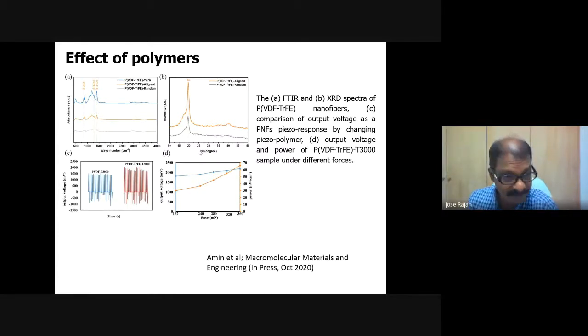But what is disappointing is when you look at the right-hand axis, where the power is noted, even with a potential on the volt scale, the power we are getting is nanowatts. It means that the current through this material is pretty poor because of the inferior current conduction mechanism in polymers. So how do we develop piezoelectric polymers with better conducting properties? What is the best strategy to improve this conductivity, and what different spectroscopies can help us in finding the targeted devices, target structures, is still ongoing, and that's where brilliant brains are required.